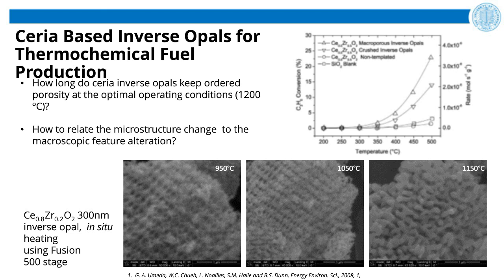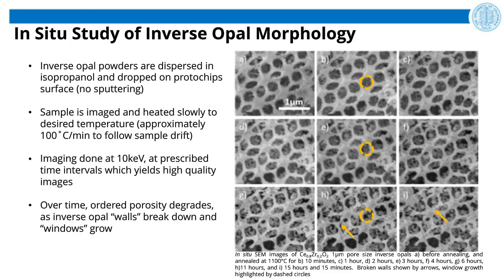This slide shows a set of SEM secondary electron images taken at an elevated temperature of 1100 centigrade. The total time of the experiment was 15 hours, and the images show that some walls get thinner. We get a change of the windows on the ceria, so generally we can observe clear degradation of the structure at this temperature.